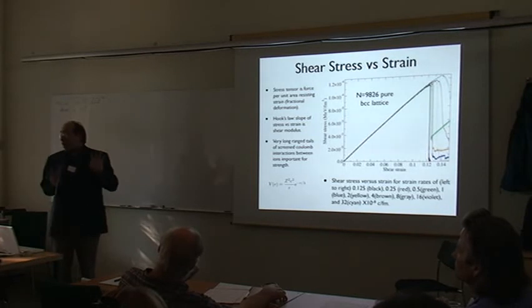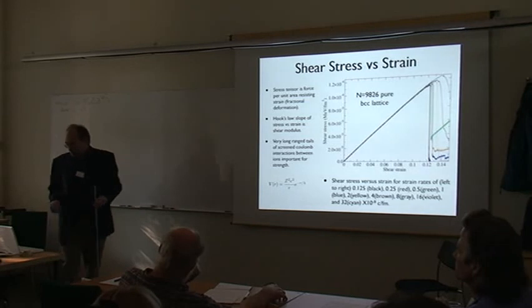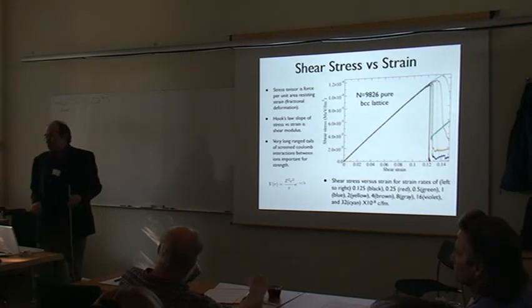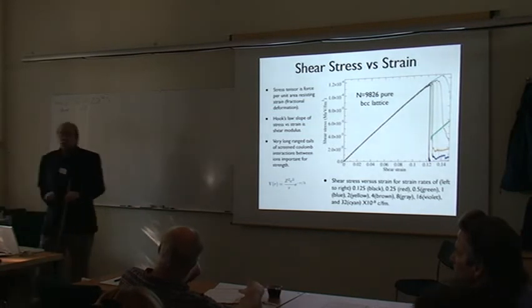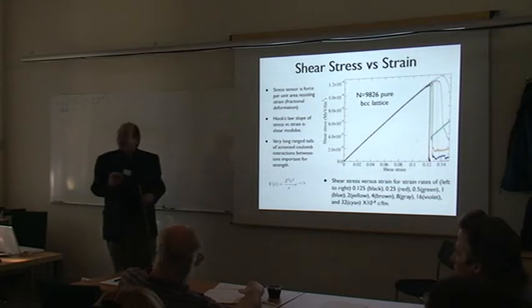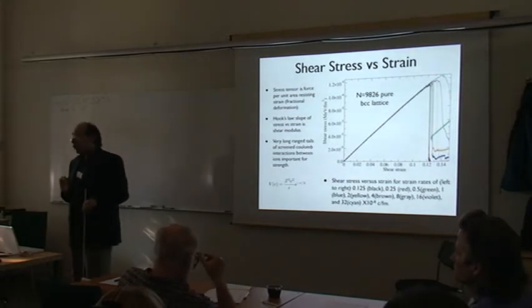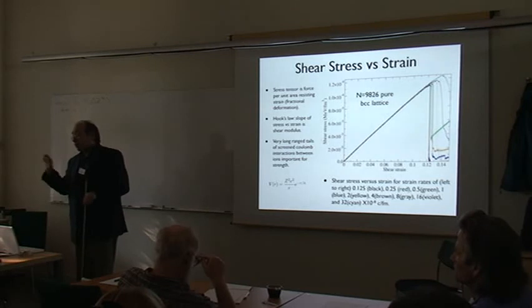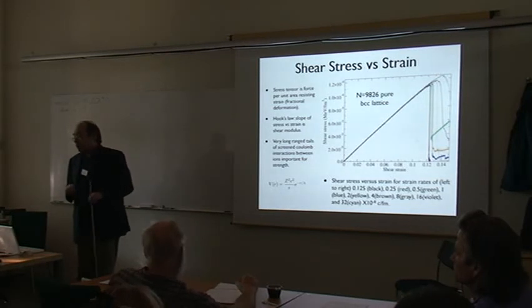And that may actually be relevant—if you have a flare, or a giant flare, it breaks and heats the system, which may cause other parts of the system to fail more easily. Is it a temperature-constant simulation? We've actually done it both ways: constant energy or constant temperature. Very similar results.